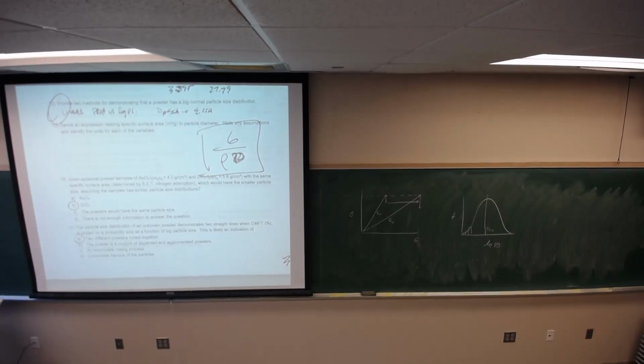Particle size distribution of an unknown powder demonstrates two straight lines of cumulative mass fraction, then plotted on a probability axis as a function of log particle size. That is like an indication of two powders mixed together. If you recall, the second answer here, mixture of dispersed and agglomerated, the agglomerated powders don't normally have a log normal distribution, so they don't behave in the same way. You don't get two straight lines. You get a straight line and a curve with an agglomerated powder.